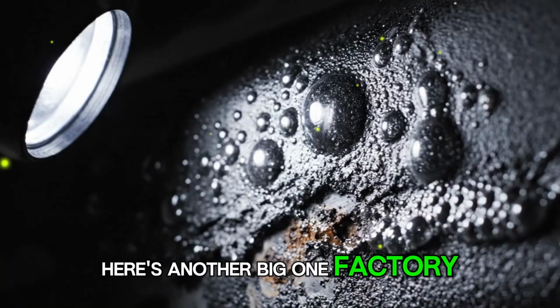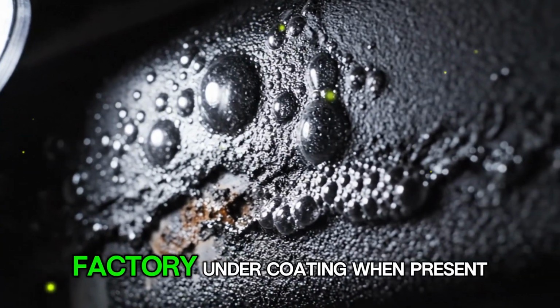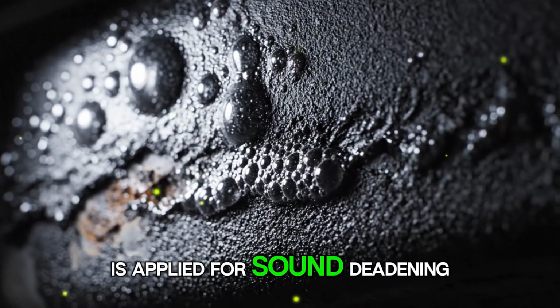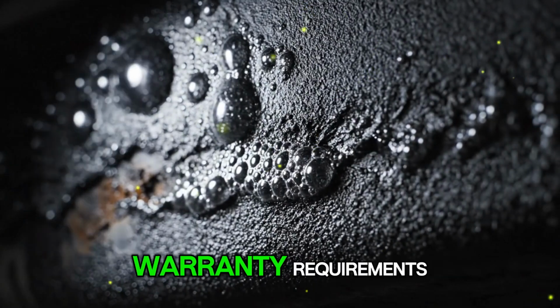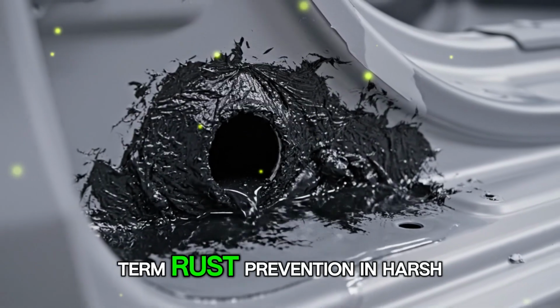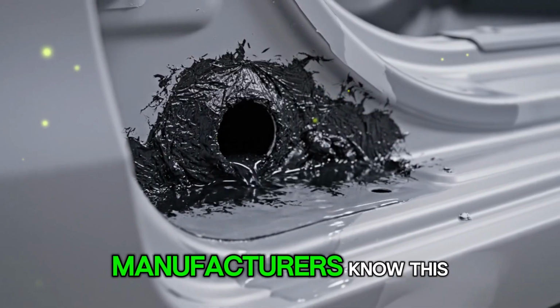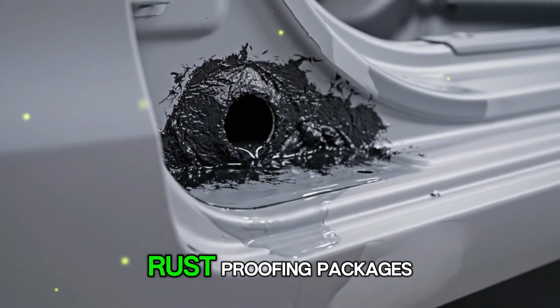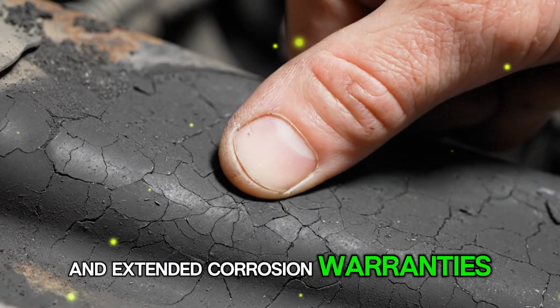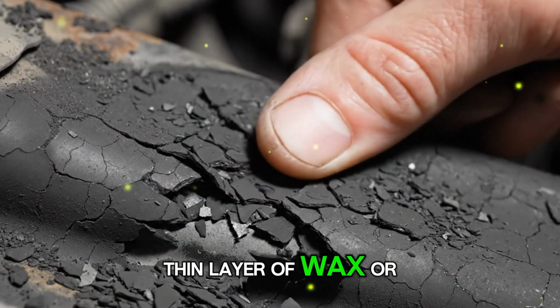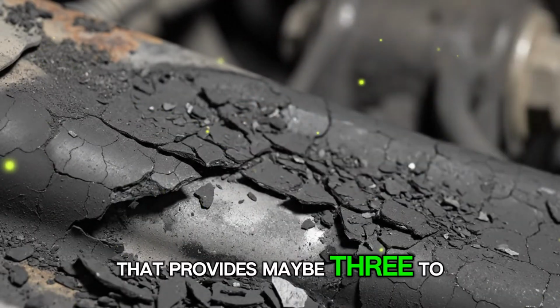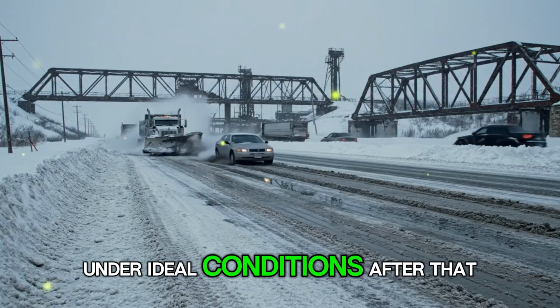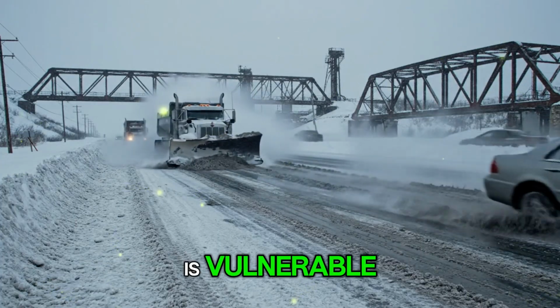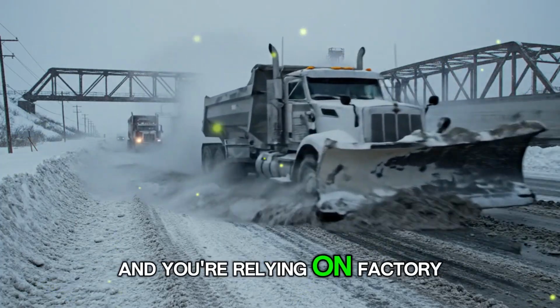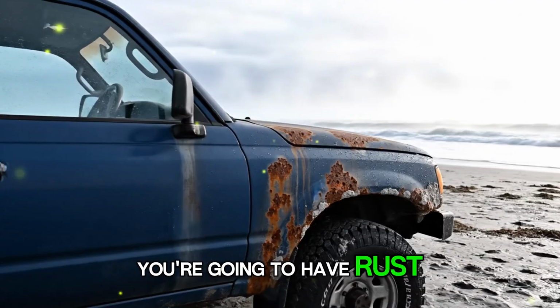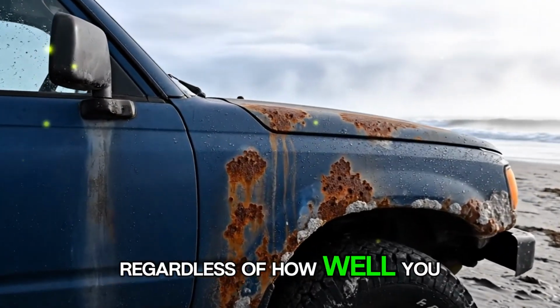Here's another big one. Factory undercoating is sufficient. False. Factory undercoating, when present, is applied for sound deadening and to meet minimum corrosion warranty requirements. It's not designed for long-term rust prevention in harsh climates. Manufacturers know this. That's why they offer separate rust-proofing packages and extended corrosion warranties. The base factory coating is a thin layer of wax or asphalt-based product that provides maybe 3 to 5 years of protection under ideal conditions. After that, it degrades, and the vehicle is vulnerable. If you live in a salt state and you're relying on factory undercoating alone, you're going to have rust issues by year 7 or 8, regardless of how well you wash the vehicle.